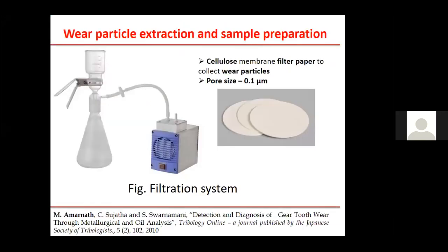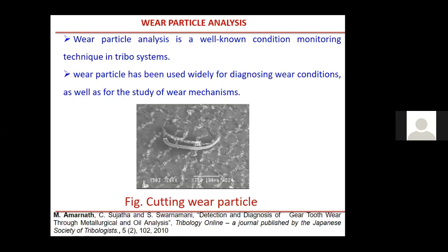It is done by using a filtration system, called the filtrogram technique. Here a vacuum pump is used, and a cellulose membrane filter paper is used to filter out the wear particles from the lubricant sample. The lubricant oil is dissolved in acetone or some other appropriate chemical for filtration, at about a 1:50 ratio. Then it is filtered using this filtration system. So you will get particles in this fashion.